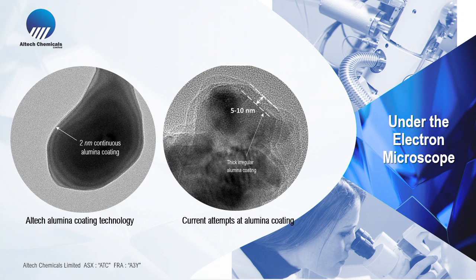They're trying to coat particles. You can see how irregular, thick layers that are going on there. And on the left-hand side is a graphite particle we coated with our HPA and our technology, and you can see a very fine layer, very continuous layer around the graphite particle at about 2 nanometers.